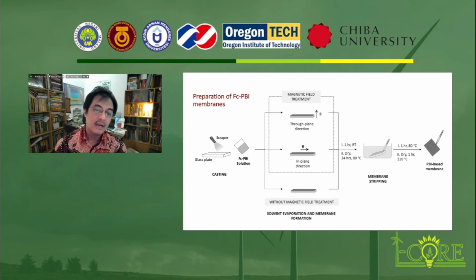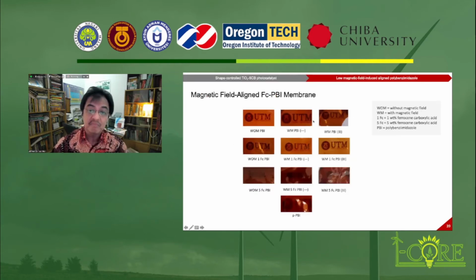Then the cast ferrocene polybenzimidazole membrane was dried in an oven and the solvent slowly evaporated, and a light brown membrane was formed. This is the picture of the membrane produced. The digital photograph of the series of polybenzimidazole-based membranes shows uniform and homogeneous brownish yellow color. It is visually observable that with the increase in ferrocene carboxylic acid content, the opaqueness increases.